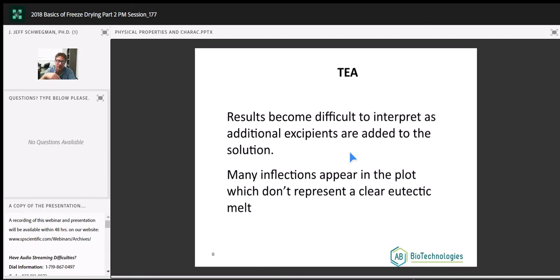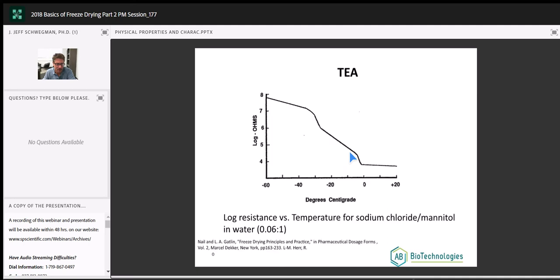Now, the results become difficult to interpret if we start to add multiple components to a formulation. Let's just walk through a few examples. This one's sodium chloride and mannitol at this ratio here. We freeze the sample, we're warming up. Boom, we see the transition. That's very characteristic of a eutectic melt of sodium chloride, which is negative 21.5. And then we keep going, we see the mannitol transition as well.